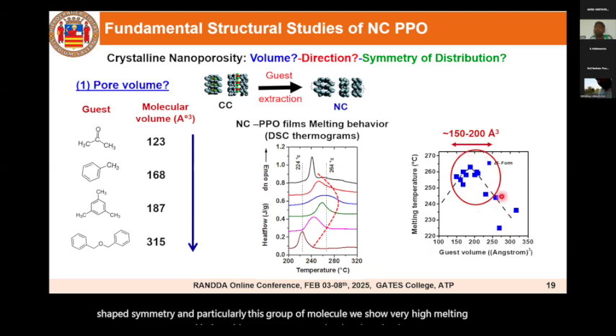From this study, we interpret that this particular group of molecules are the best fit in the co-crystalline phase. As a consequence, they form a stable nanoporous crystalline phase. From this interpretation, we understood that this PPO film has a pore volume in the range of 150 to 200 cubic angstroms. That is the first question we answered.